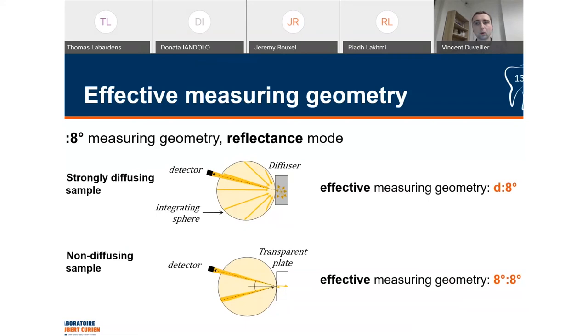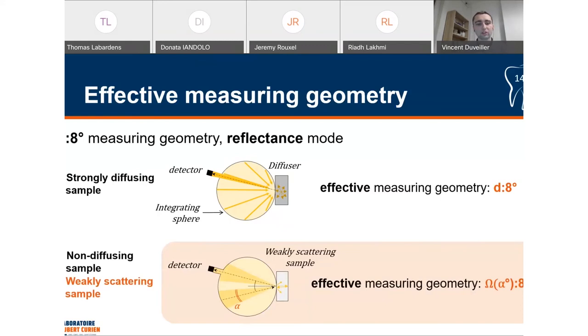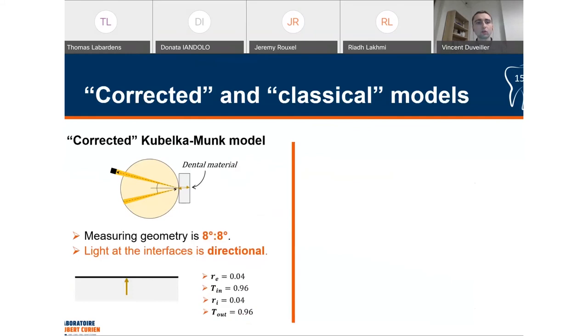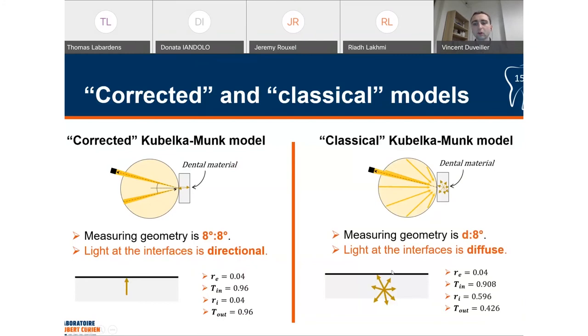Now, for our dental materials, which are weakly scattering, the effective measuring geometry is somewhere between the two cases, between the hemispherical directional and the bidirectional geometry. However, we have observed that they behave much more like a glass plate than like a white sheet of paper because of their high translucency. So we propose the corrected Kubelka-Munk model, which assumes that the effective measuring geometry is bidirectional. Remember that the Saunderson correction depends on this effective measuring geometry. So it changes the parameters for the correction. So we have this corrected Kubelka-Munk model, but we still have the classical model, which assumes that the light at the interfaces is diffused. So we will try both models and assess their accuracy to predict the reflectance and transmittance factors of a dental material.